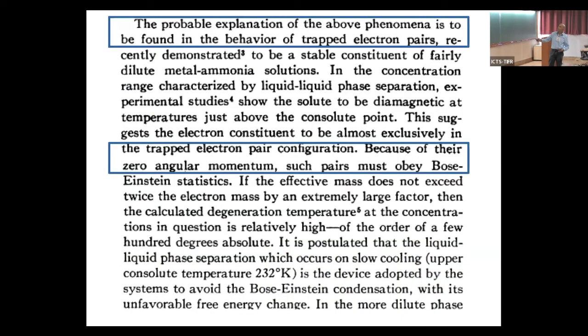The probable explanation for the above phenomena is to be found in the pairing of trapped electrons, because there are experimental indications. Look at spectroscopically about trapped electrons. They form a singlet. And you can see the singlet excitation gap. So they form a singlet pair. Now this trapped electron pair, because of their zero angular momentum, such pairs must obey Bose-Einstein statistics. This was Ogg's theory before BCS theory.